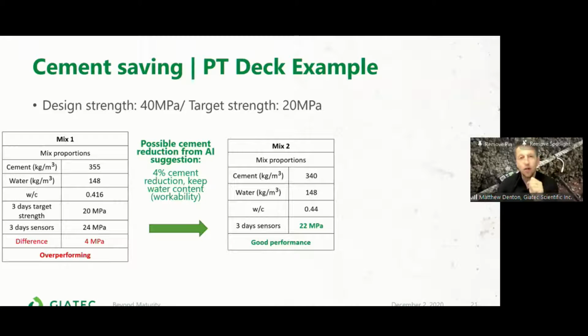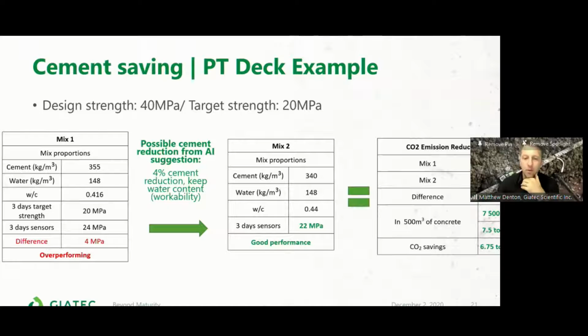However, now the strength we were actually reaching on day 3 was 22 MPa. So we're about 10% above the target strength, which gives us good performance versus that overperformance that we were expecting. What did this result in? At the end of the day, we could reduce the actual cement required per cubic meter. It's a very basic equation. We could say, okay, from 355 to 340, we reduced 15 kilograms in 500 cubic meters of concrete.